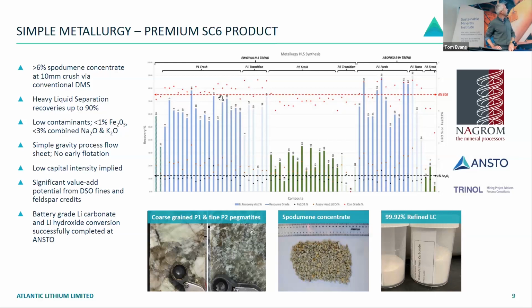But you can see the height of these bars is your recovery in HLS. So this is heavy liquid separation. And on average in the P1s, you're looking here at that 70%, but up to 90% recovery. And you're producing from a head grade, which is your brown dot here, of around about 1.5 and up to 2%. You're getting up to a 6% concentrate easily. The red dots, that red line is 6% lithium oxide.